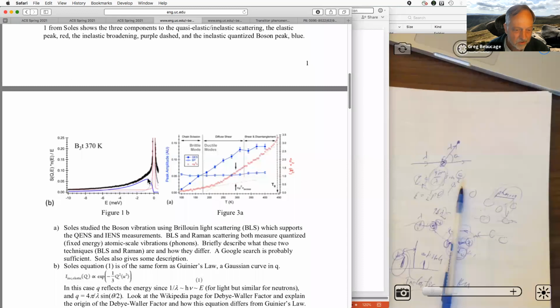So they can distinguish between those two by curve fitting this and by using a function for this broadening, which is this Debye-Waller function, which looks exactly like Guinier's law, strangely enough, right? And it's not that strange because this is a Gaussian function, right? So that Gaussian curve is like your general fallback, like anytime you see something that leads to randomness, you're going to use Gaussian. I mean, like a grade distribution, you use a Gaussian distribution, the bell-shaped curve, right? So that's your fallback answer to anything that looks like you have a sharp thing and it becomes broader. You say, oh, it's Gaussian. That's the first thing you do, right? So it's not surprising that this thing looks just like Guinier's law because they're both talking about random things.